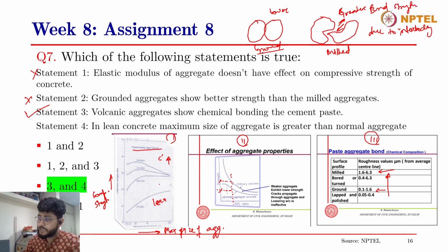When you go further increasing the cement content, the compressive strength increases with the increase in the maximum size of aggregates, and then it reduces as you further increase the maximum size of aggregate. So in high strength concretes, which have high cementitious content, as you keep on increasing the maximum size of aggregates, the compressive strength will in fact reduce, right? But in case of lean concretes, which have low cement contents, as you keep on increasing the maximum size of aggregates, the compressive strength increases. So the statement 4 is a correct statement.